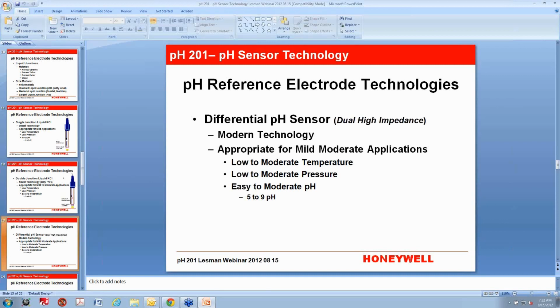It is a better technology than using a pH sensor that has a liquid fill inside if you're in a process situation. The downside is that they're expensive because they have two full-on pH measuring electrodes in them, and they will only work with an instrument that's designed to function with a dual high impedance or a differential pH sensor. They're appropriate for mild to moderate applications, low to moderate temperatures and pressures, what I would call easy to moderate pH, which is between 5 and 9 as well.